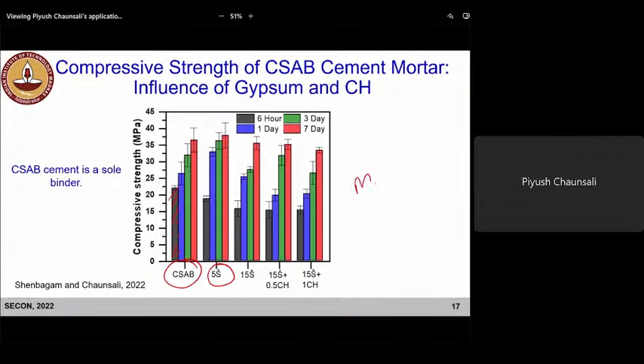It all depends on the M value, as we discussed earlier. If we increase the gypsum to C4A3S ratio, that will lead to expansion. So we wanted to understand, if we are getting expansion, does it compromise or affect the strength? You can see some influence on early age, but the overall 7-day strength is more or less the same, right? So up to 15% of gypsum addition we looked at.